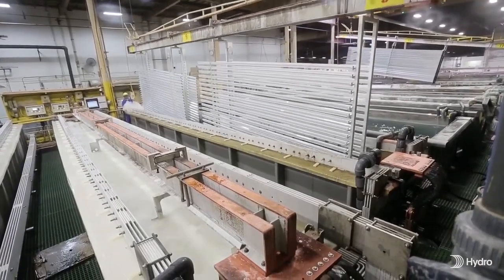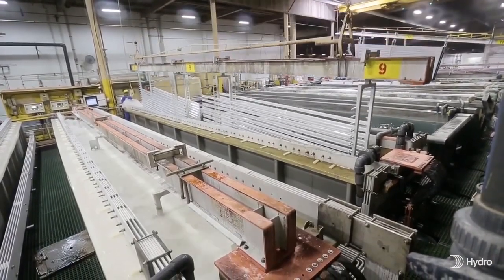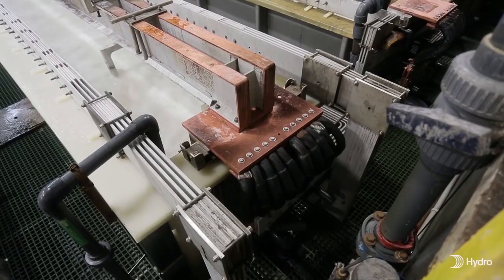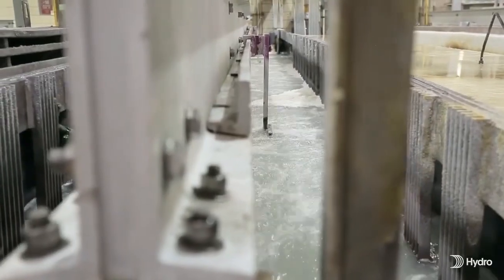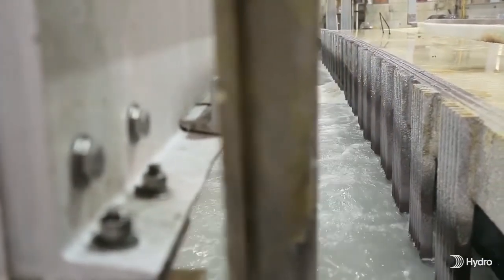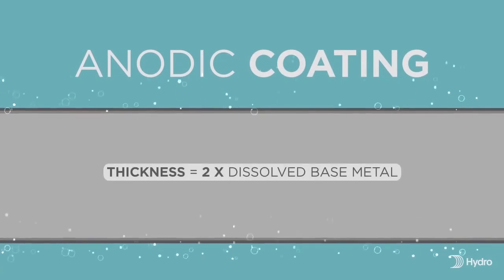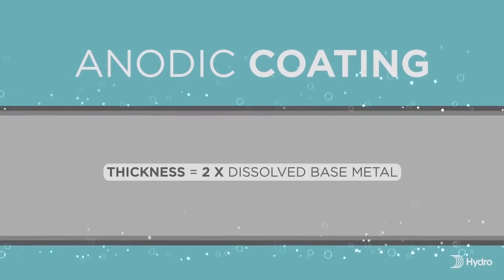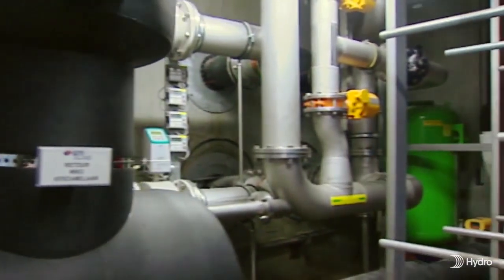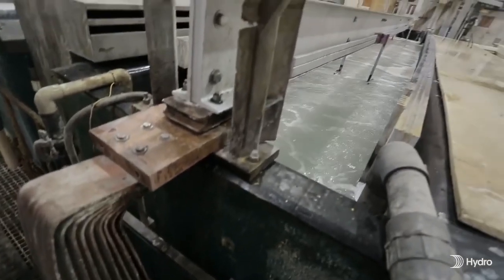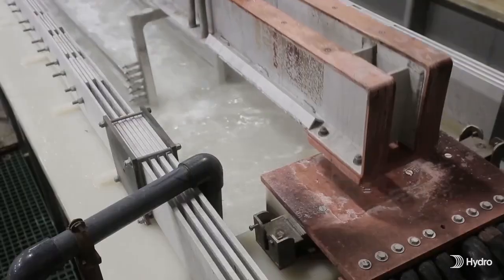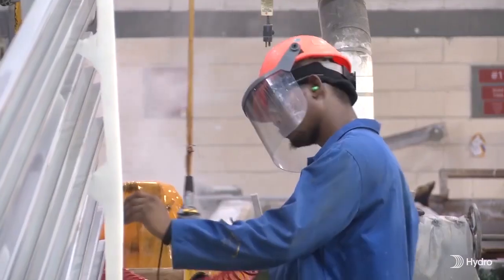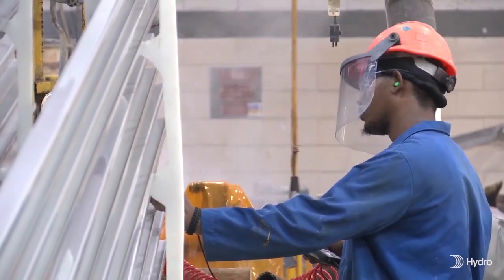After additional rinses, the material is transferred to the anodizing tank and immersed into the electrolyte of sulfuric acid. An electrical current passes through the tank, causing the release of oxygen ions and the growth of the anodic coating. The anodic coating both enters the substrate and grows outward, creating a fully integrated layer. The anodizing process generates a lot of heat, so the electrolyte must be refrigerated to maintain the proper temperature. Immersion time is carefully monitored, since this is how the desired thickness of the coating is achieved. Periodic testing ensures the proper results.